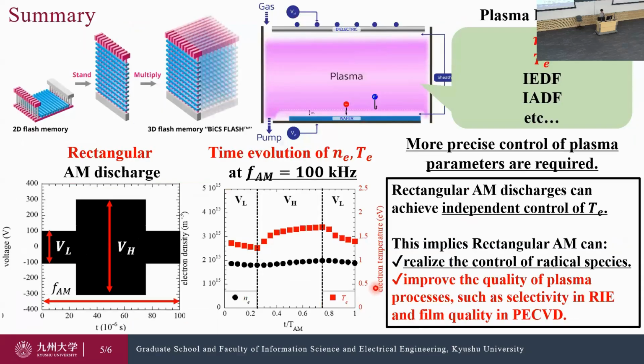Finally, here is my conclusion. With the 3D stacking of semiconductor devices, higher precision control of plasma parameters, including electron density and electron temperature, is increasingly required. In our study, we demonstrated the potential for achieving partial independent control of electron temperature using rectangular AM discharge. These findings suggest that rectangular AM discharge can contribute to radical control in plasma processes, potentially improving selectivity in RIE and film quality in PECVD.